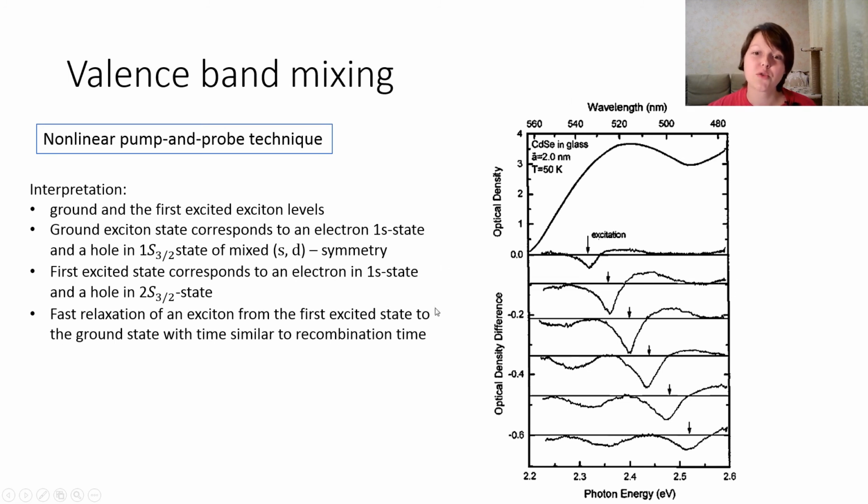Here I show you the results of nonlinear pump and probe technique on the basis of the spectral hole burning inside of the absorption spectra of cadmium selenide nanocrystals in glass. Here we can see that while monotonically tuning the excitation energy and wavelength, finally we obtain not one hole burnt in spectra, but two holes simultaneously.